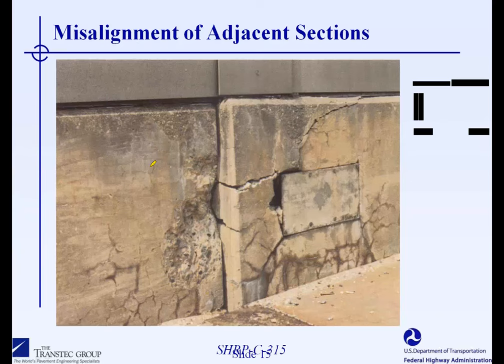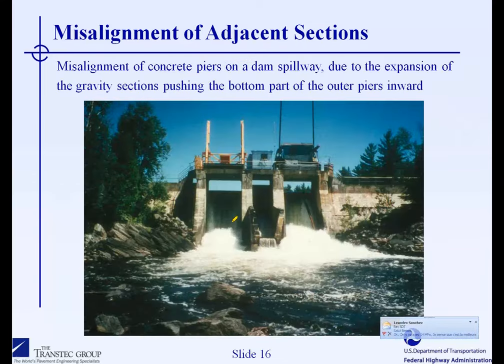Since AAR will not necessarily develop at the same rate or the same extent between the different members of a concrete structure, one thing that you could see also in AAR affected concrete structures is misalignment of adjacent sections in a concrete member. As I said, the main reason for that could be differential expansion between one part of the structure and the other. This can be due to a different concrete mix design, different alkali content, different exposure conditions to sun, to rain, etc. This difference in the conditions inside or outside the concrete element can result in different expansion rates, which will result in relative movements and misalignment of different sections in the concrete structure.